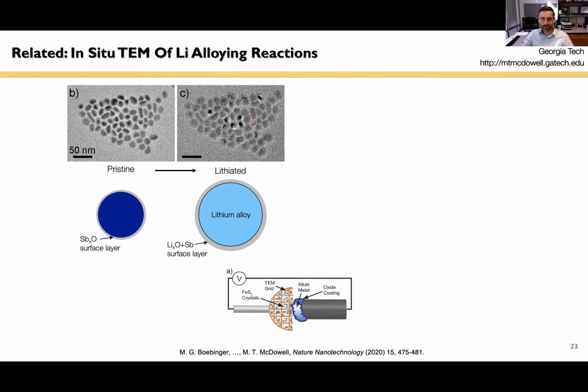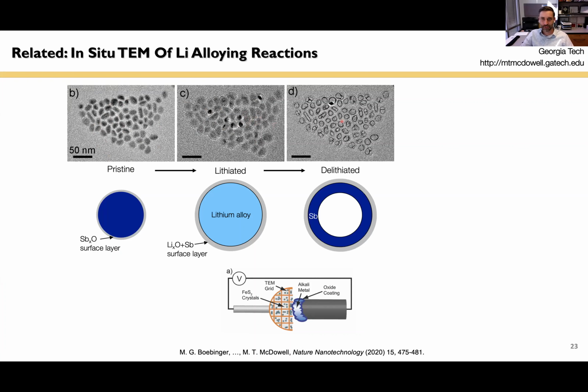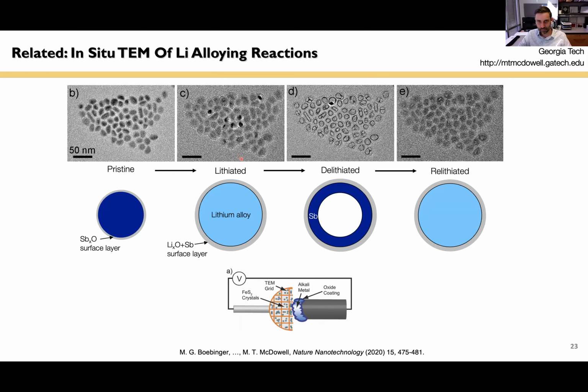But very interestingly, we found in this particular study that when we delithiate these crystals, there's this formation of these hollow structures. What's happening here is we have this outer oxide shell, which is constraining the contraction of these materials. And so it prevents them from shrinking. Instead, it causes the pure antimony to go to the surface, as you can see in the schematic down here. So I show this just to illustrate that we do experiments to probe fundamental reaction mechanisms in alloy materials. And in fact, we found some pretty interesting mechanisms. The reason this sort of thing happens is because we have these very large volume changes, which is atypical of general materials transformations.